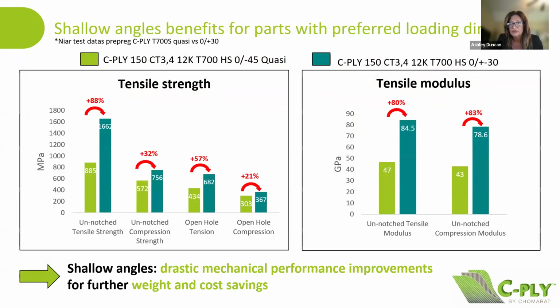So here's another series of test results from NIAR. This time, we're comparing 150 GSM C-ply laminates with a preferred loading direction. One laminate incorporates 45-degree angles, and the other incorporates 30-degree shallow angles in the preferred part loading direction. The bluish turquoise bar represents the shallow angles laminate. Note there's a significant improvement in mechanical performance by incorporating shallow angles in the preferred loading direction. By strategically positioning the fibers in the most optimum direction to carry the load, could you reduce your part laminate plies or reduce your overall part weight?